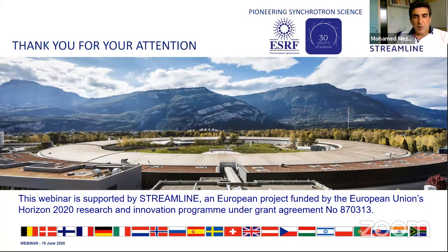Yes, for static experiments there are several methods, but the most standard one is called the ruby fluorescence method. Inside the cavity next to the sample, you place a little ruby chip that is a few microns. It's also another advantage of the diamond: diamonds are transparent, so you can go through them with X-rays, but you can also go through them with lasers.